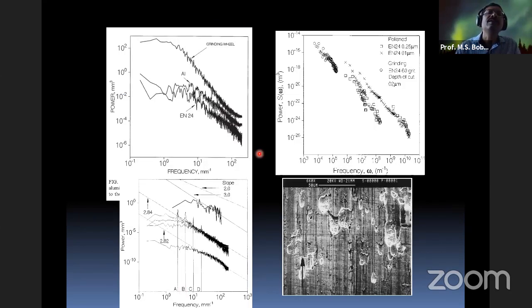So if you see, there is something called cutoff length. This is decided by the manufacturing process, beyond which there is no variation like this. Otherwise, the surface roughness produced, because all these surfaces are produced by a fracture process, the fracture is inherent, gives us this variation of how the square of the amplitude varies with the frequency or the wavelength. 1 by wavelength is the frequency, as I mentioned. And this is for various turned surfaces. The fractal dimension, which I did not talk about, is decided by the slope of this line.